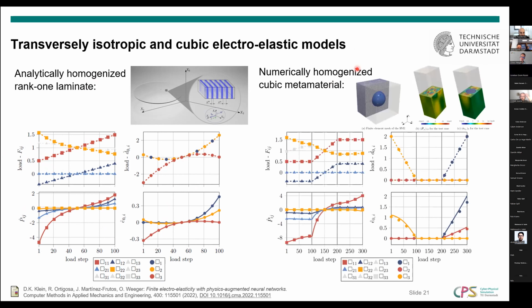Same thing also for the case of a metamaterial, which we homogenized numerically, which results in a cubic material symmetry, cubic material behavior, where again we apply some complex combination of deformation and electric displacement field to evaluate the model, and we get a very good agreement of the behavior of the microstructure and the prediction of the effective behavior that we get from the neural network.